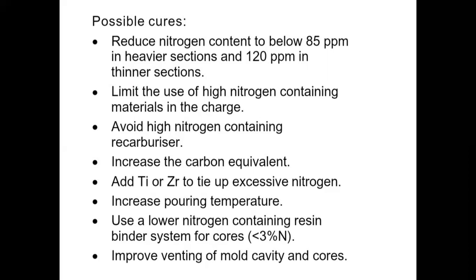Avoid high nitrogen-containing re-carburizers. Increase the carbon equivalent. Add titanium or zirconium to tie up excessive nitrogen.